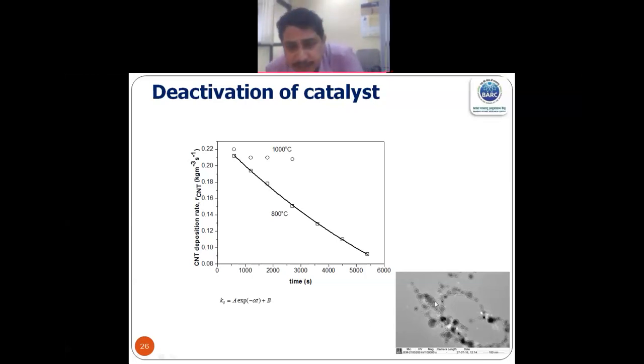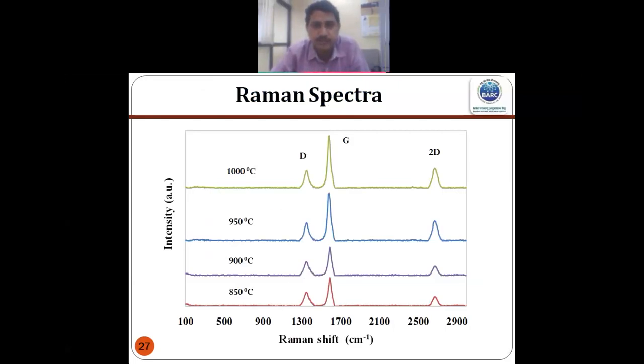Here you can see what happens when a catalyst gets deactivated. I am showing a typical TEM image, where the catalyst particles are surrounded by other forms of carbon like amorphous carbon, which covers the catalyst particle and does not allow further growth of carbon nanotubes. So how do we characterize this? Once we get carbon nanotubes, how do we characterize them?